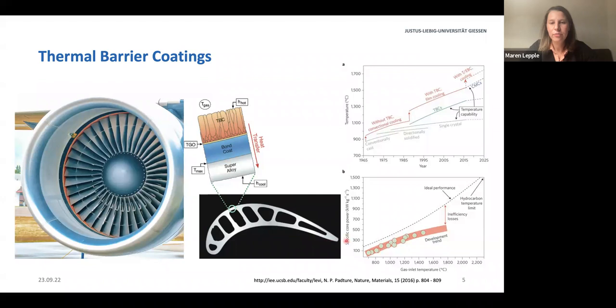And here you can see, for example, an airfoil with the gas channels here, which are used for active cooling. And usually, what you can see here in the bright phase is the superalloy, usually a nickel-based superalloy. And on this superalloy, a bond coat is applied, which provides good adhesion between the superalloy and the thermal barrier coating or the ceramic coating, and also provides some oxidation resistance because the bond coat forms a thermally grown oxide layer, which is alumina during the operation, which provides some protection against further oxidation. And then on this, the thermal barrier coating, so the ceramic material, is applied, and it's usually a very porous structure, either lamellar or also just porous, and it has a very low thermal conductivity.